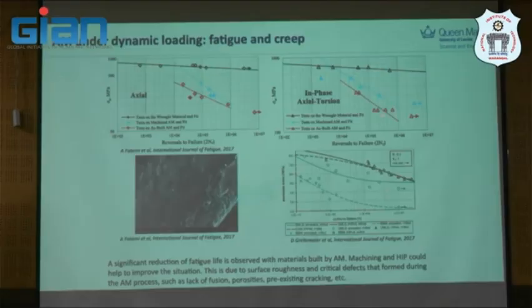And this is quite clear. It really happens. If you machine it, it improves the property a little bit, but not very close to the rod material. But if you as-print it, I don't say the worst, but you still get about probably a million cycles of life of material, but it's not as good as 100 million cycles of the material life. But anyway, this is something to consider. I throw this question to the mechanical engineers to try to solve and understand. That's why the detailed microstructure is so important to dictate the life of the material in this case. So no doubt about it.